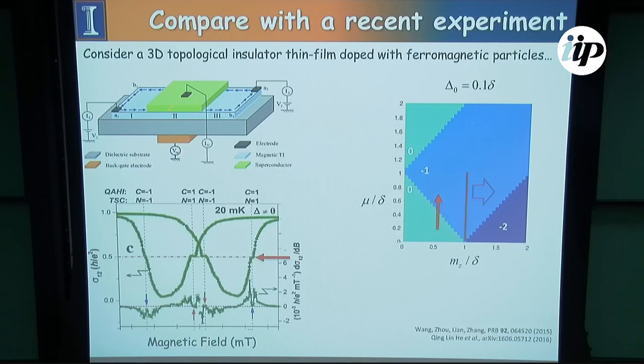Okay. But this is an experiment by the UCLA group, which is filtering its way through science, I think, where they actually took a thin film topological insulator and doped it with chromium. And so they were able to create a quantum anomalous Hall state. So they have a quantum anomalous Hall state that's running around the outside of the topological insulator. They put an S-wave superconductor on top of it, and they see these plateaus at certain magnetic fields at half E squared over H.